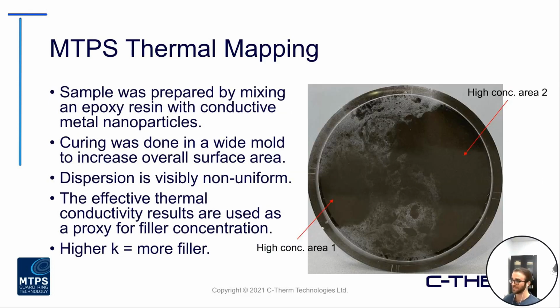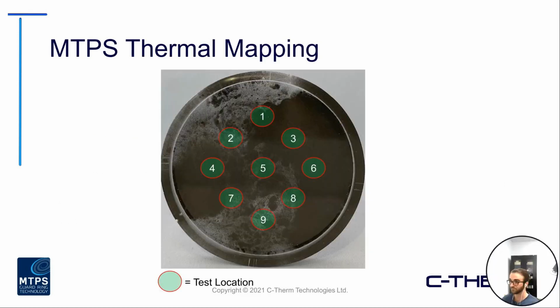The example we're taking a look at today is a very simple example, but it was an epoxy resin that was cured with a conductive metal nanoparticle dispersed in the matrix. This was done in a wide mold to really increase the overall surface area, and very visibly, right out of the gate, you can look at that image on the right there and see some quite non-uniform dispersion. However, we're going to use this example to just illustrate how the effective thermal conductivity measurements taken across that surface can be used in this instance to correlate to the filler concentration, where a higher effective conductivity value will be indicative of more filler in that specific location.